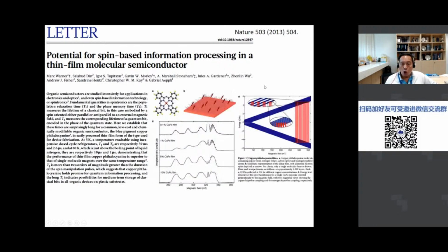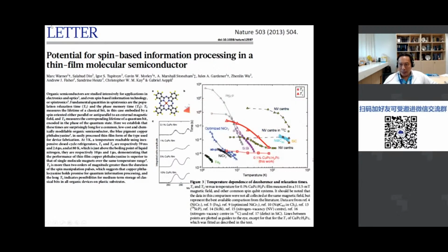Essentially, they studied copper phthalocyanine, this molecule over here. So it has a copper center and phthalocyanine attached to it. And they used, I think, ESR measurements, and they measured basically the spin property and the coherence, decoherence, and relaxation times, and found that at near room temperature the coherence times are fairly decent. So that's not far from those in the NV centers. This is diamond NV centers, currently being the forefront materials. So there's potential to use molecules.